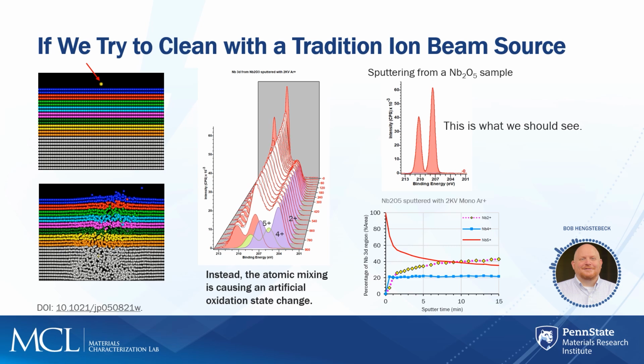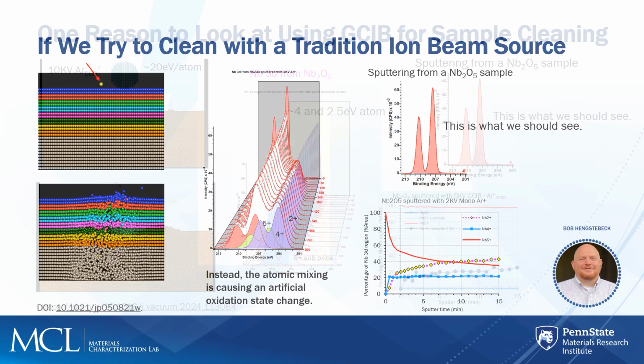So if we had an organic coating on a surface and you wanted to know what the chemistry was at that interface, and we had to remove all the organic, by the time we got down to the actual interface, all we would see is this cluster of Nb +5, +4, and +3. And you'd have to ask yourself, is that real? And this example is showing you it wasn't.